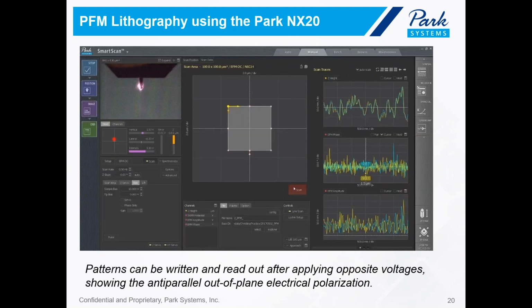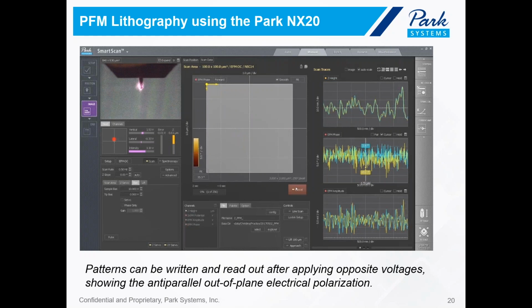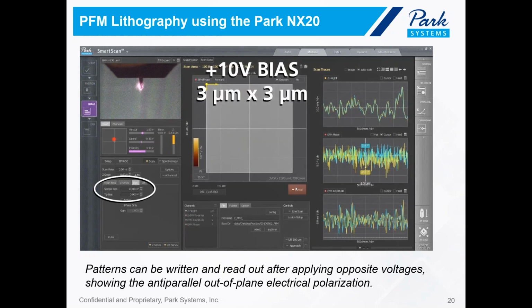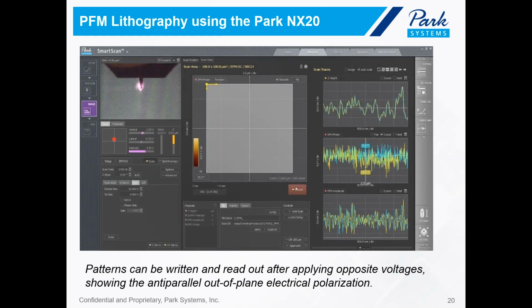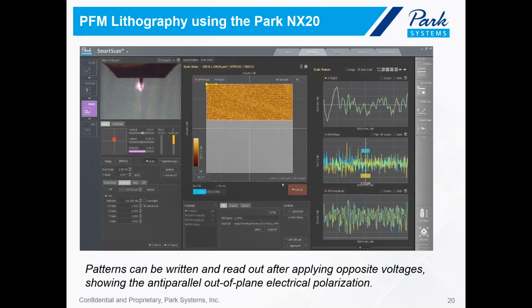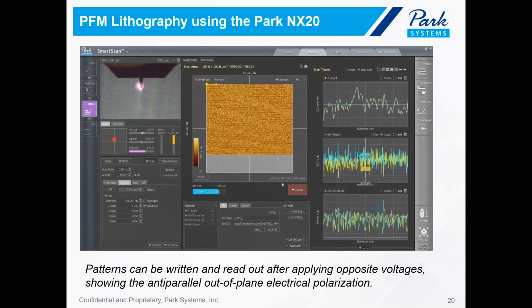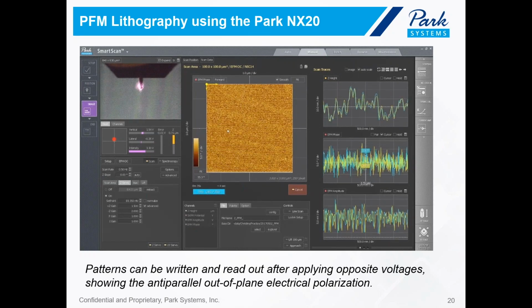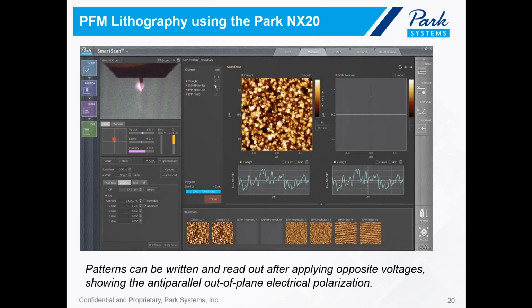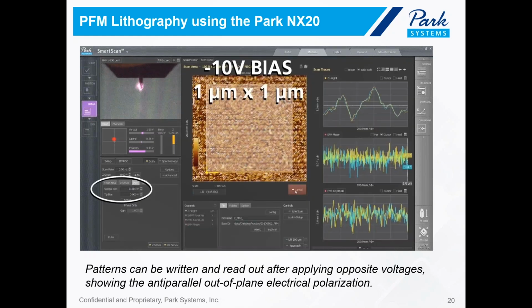So right here, I have the experiment in action, and I'm gonna play and show you what we did. So to start, we input a sample tip bias here from the software, positive 10 volt, and we scan the 3 micron by 3 micron region. So here is the scan. This is a phase channel, so we don't expect to see much. But here is the topography channel, and you can see we monitor the topography and phase separately.